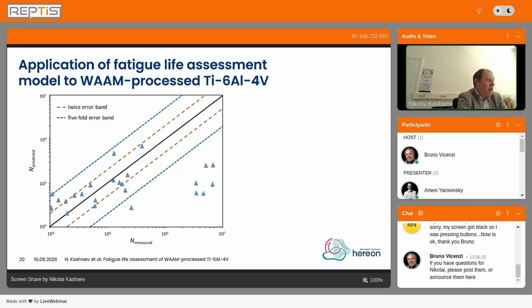And here are the results with regard to experimentally obtained results and predicted results using our model. You see, we are quite good with regard to twice error band or five-fold error band, but we have some specimens which showed lower fatigue life with regard to the predicted one, but we still are at a good level with regard to conservative fatigue life.